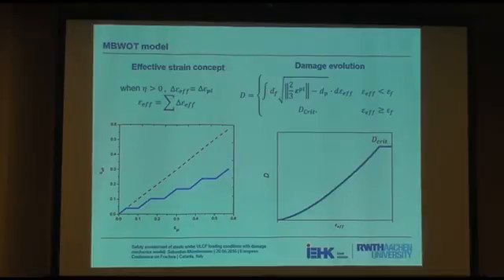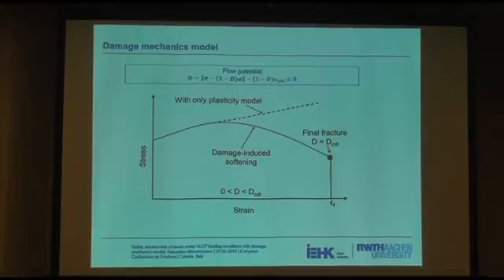Okay, and there's also a ductile damage evolution law. There's no threshold values, no damage initiation criterion, so we assume that ductile damage will initiate from the onset of plastic yielding, and it can increase until a critical damage value is reached, and there's a certain function to describe damage evolution in between. Of course, we need to couple the damage evolution back into our yield potential in order to describe the influence of damage on the constitutive behavior. If we would only apply a plasticity model, we would always run into the hardening phase, but here there can also be a damage-induced softening, and this shall be expressed as well by the model.